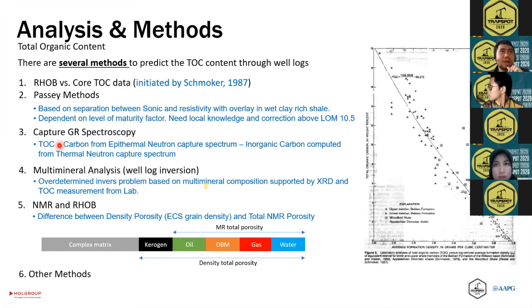You also can calculate the TOC from the capture gamma ray spectroscopy, which takes the carbon from the epithermal neutron capture spectrum minus the inorganic carbon. From that, we will know the organic carbon from this measurement. This kind of method was also used for the LECO measurement in the laboratory. With LECO, that I mentioned previously, they calculate the total carbon minus the inorganic carbon, and they will find the organic carbon itself.